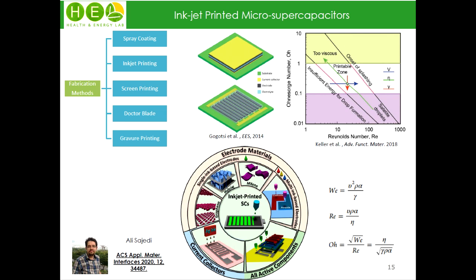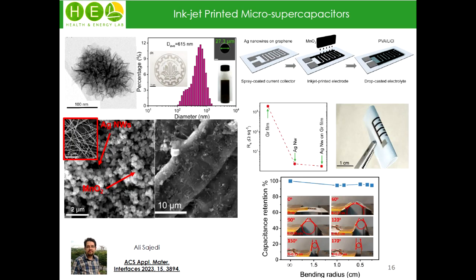In all our research, we started with manganese oxide flake-like structure using a simple hydrothermal method, and these flakes were connected in a flower-like structure with a good size, well below the size of printer nozzles to avoid clogging effects.